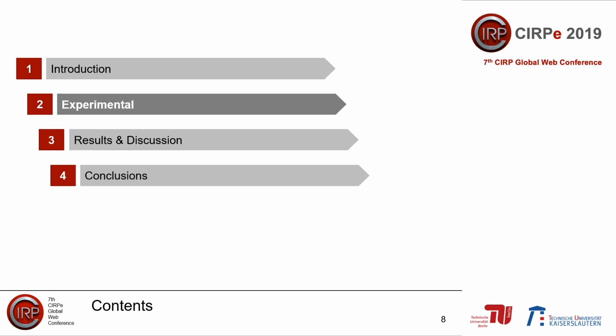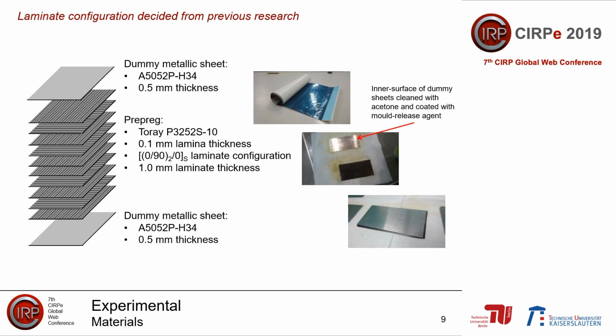So, on to our experimental research. In this research we used this laminate configuration. Our prepreg is of 0.1mm laminar thickness. We used 10 layers in this configuration, giving us a total laminate thickness of 1mm. Then we have our dummy metallic sheets constituted by aluminium alloy, and we coat the inside surface of our dummy metallic sheets with mold release agent before sandwiching around the prepreg.